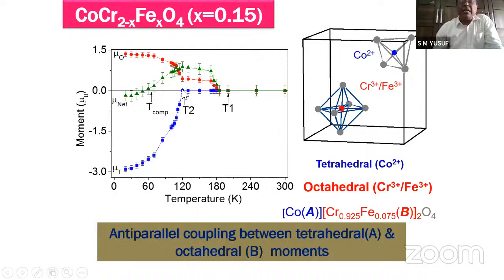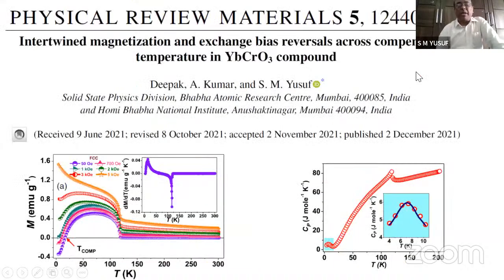So this is definitely a clear deviation from the mean field concept, because as you all know, the mean field states that once one magnetic site gets ordered, it produces an internal field, and the other site will also get ordered. That is usual, but that is not happening. But one more interesting point, when this tetrahedral site gets ordered, we also see a second jump in the growth of magnetization of the octahedral site. And the green one is the net one, considering both octahedral and tetrahedral. You know, in the ferrite structure, how many octahedral and how many tetrahedral sites there are, and you have to also take the cation concentration and so on. So the net one is definitely showing the magnetization reversal and zero magnetization at this temperature. So this is a microscopic picture of this magnetization reversal.